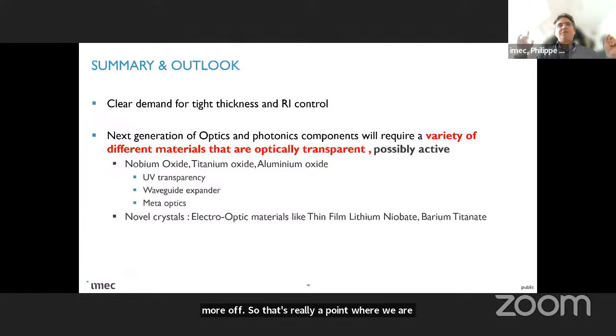When you go towards the edge of the wafer, usually this is where the machine vendors have not always been designing that so carefully. But rest assured that the etching guys have also been giving away the last centimeter of the wafer usually. At least on 200 millimeter for the older generation tools; on 300 things are a bit better. And what is also very important for us is the refractive index control. Some people don't always mention that, but having a very uniform control is nice for the thickness, but actually what matters is the refractive index, and there we are into